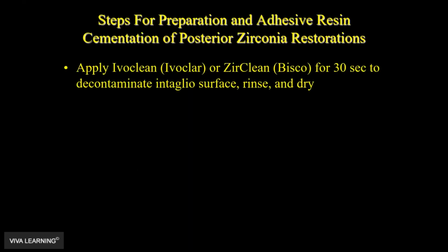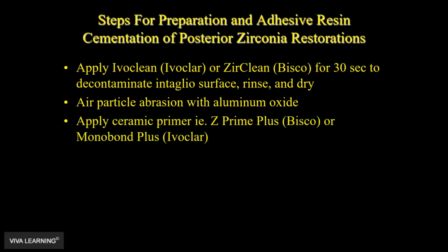So our cleaner, what we decontaminate with, you can use Ivoclean. I like Bisco's ZirClean. You do it for like 30 seconds. You decontaminate the intaglio surface. You rinse and you dry. Then you air particle abrade with aluminum oxide. We place our ceramic primer, Z Prime Plus.